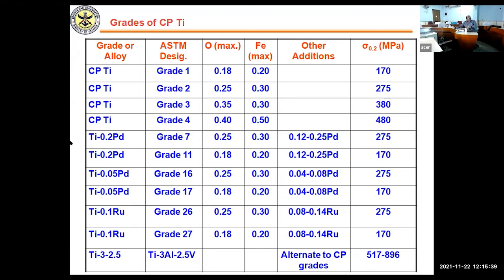And here I'm just showing you the different grades of CP titanium and the alpha titanium alloys. You can see grade 1, grade 2. What is the difference is the amount of oxygen. Oxygen is an alpha stabilizer and also a strengthener. And here I'm showing you the 0.2% yield strength. And as you see, as the oxygen content is going up, the yield strength is also going up. And then these modified alloys with palladium and ruthenium, and these are the yield strengths.